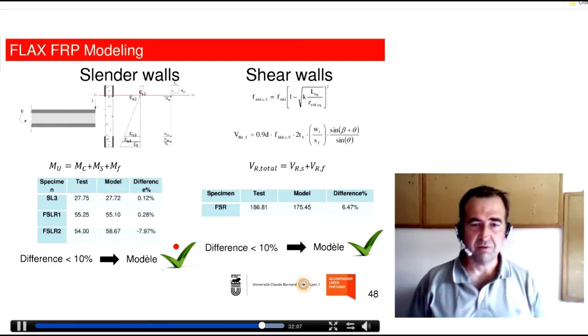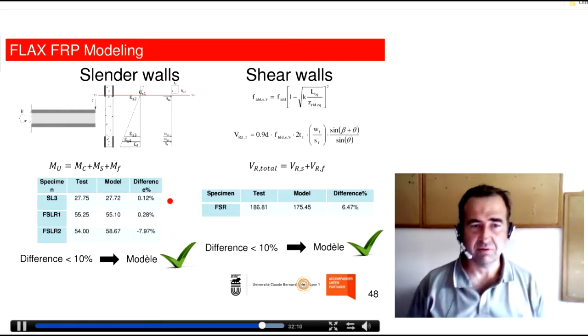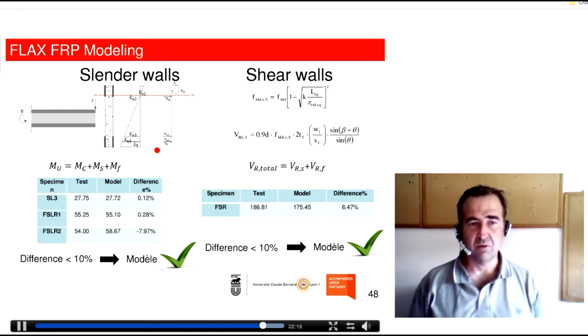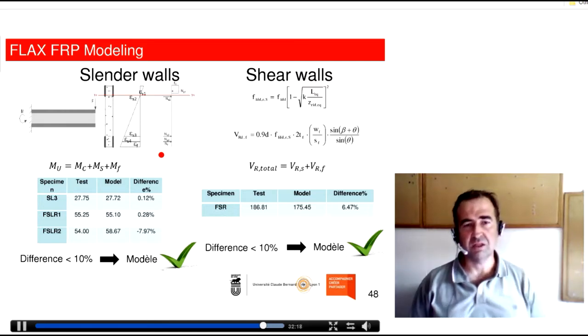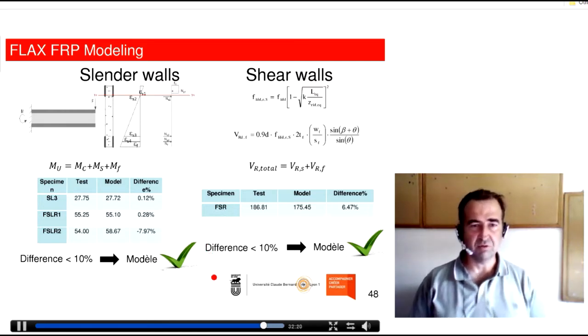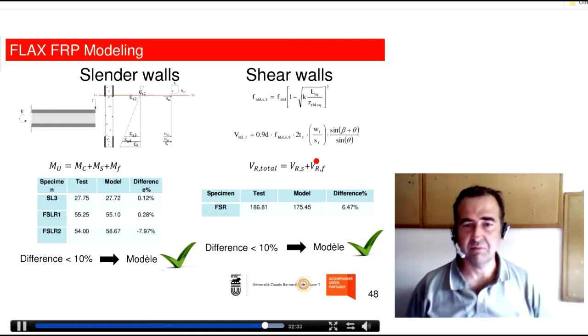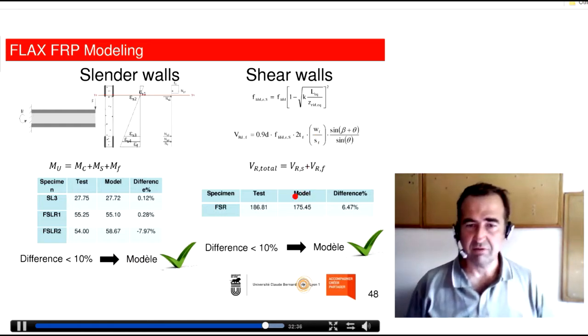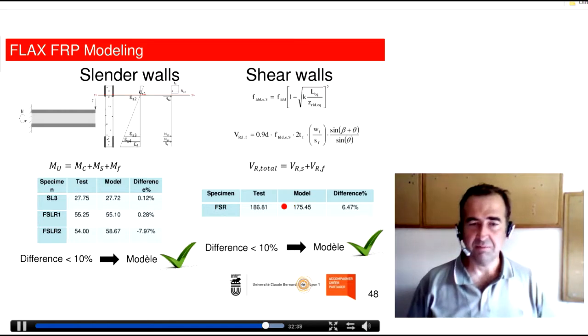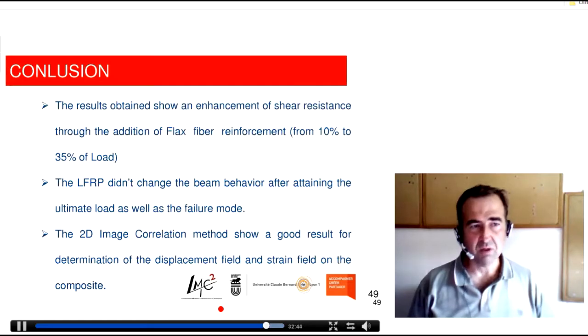In order to check whether this kind of flax fiber may modify the way that we calculate the wall, we use a usual calculation method developed in, for example, Eurocode 8 part 3. What we have seen is that the contribution of flax fibers may be calculated more or less as for carbon ones, and that if you have the real mechanical properties of these fibers, you are able to calculate very precisely the experimental load capacity of this wall.